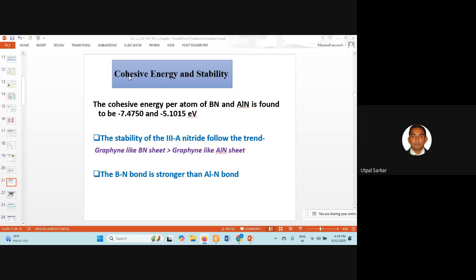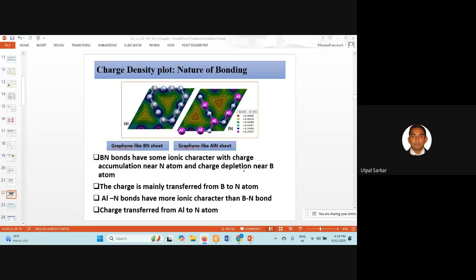We can also do the cohesive energy and stability. The cohesive energy per atom for BN and aluminum nitride we have calculated, and it is found that the graphene-like BN sheet is more stable than the graphene-like aluminum nitride sheet, and the BN bond is stronger than the aluminum nitrogen bonding. So these are the charge density plots.